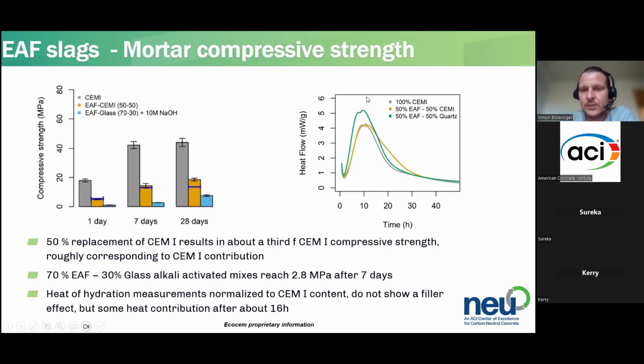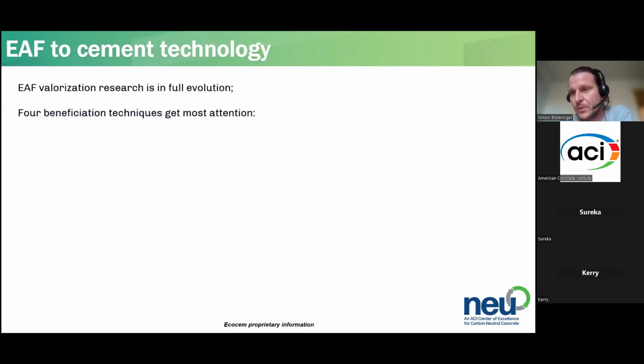Also, if you look into the calorimetry image here on top right, you can see that if you normalize by cement, you get for the first 10 hours exactly the cement reaction from the 50% slag and cement mixes. So not even a filler effect that would result in something like this, like the green curve illustrated by quartz powder here. So for the first hours, this is clearly inert, and there may be something coming out of the EAFs at later ages. So if we want to use this as an SCM, we would need to enhance the reactivity somehow.